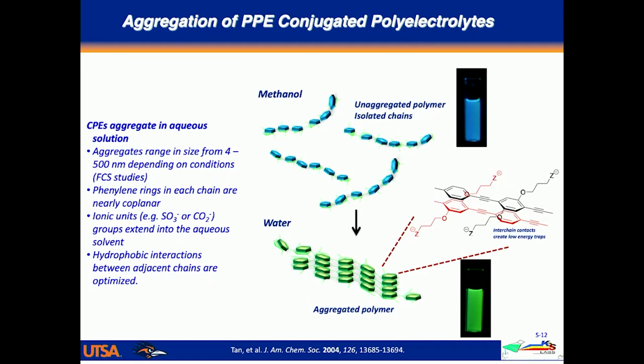And after doing quite a bit of work over several years, we've come up with a model which basically understands the idea that these polyelectrolytes are actually existing as mostly unaggregated individual chains in low molecular weight organic polar solvents like alcohols. But in water, these materials aggregate, and they form structures that we believe have some organization. But in particular, because of the aggregate structure, there are close contacts between the polymer chains and the arylene units, and those give rise to what we call an excimer-like excited state, meaning that when you excite the material, the excitation is delocalized over more than a single chain, and that gives rise to this very profound shift in the emission spectrum and the broadness of that emission.